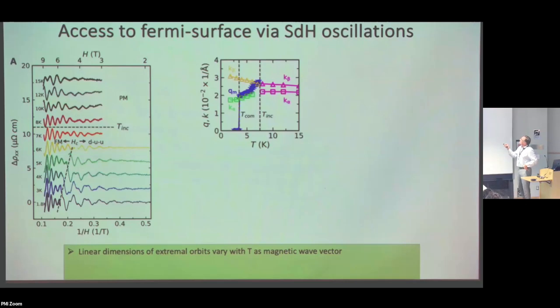So now I'll say a few words about the electronic transport properties. The idea is that we will use transport, in this case Shubnikov-de Haas oscillations, to learn about the underlying Fermi surface. And the general scheme is that we would like to understand how the Fermi surface has impacted the particular periodicity of this incommensurate magnetic structure. Obviously you can do that with band structure calculations, but it's usually difficult to really fix the chemical potential, which can have a very big impact on the nesting conditions. And so we're doing the transport properties to determine what the chemical potential is in the electronic band structure, and then we can make the comparison between the wave vector observed in magnetic neutron diffraction and the nesting conditions from the band structure calculation.